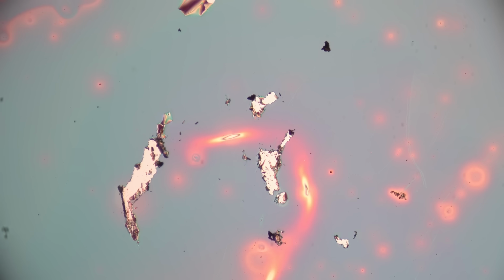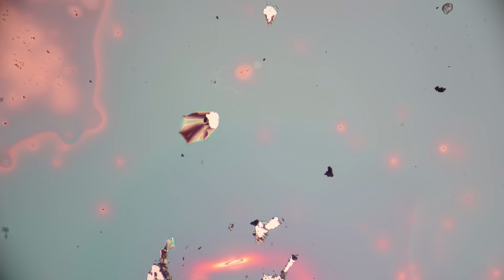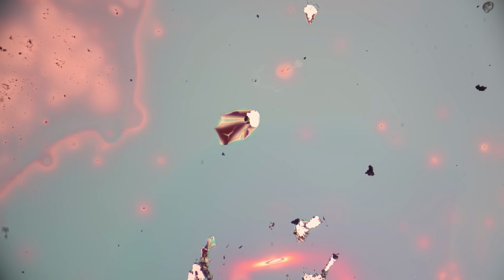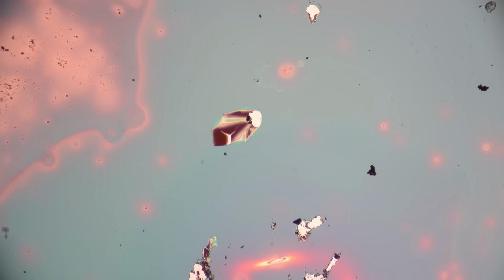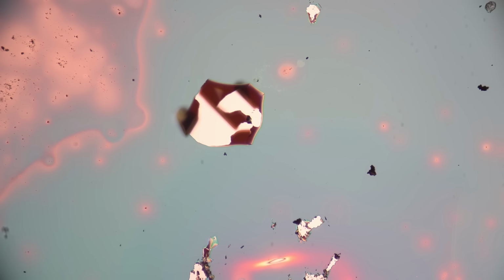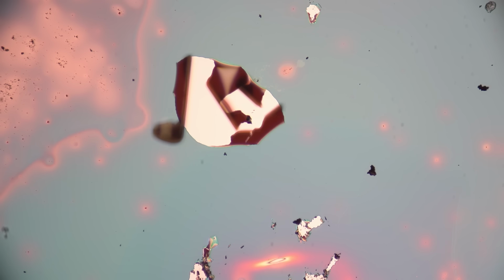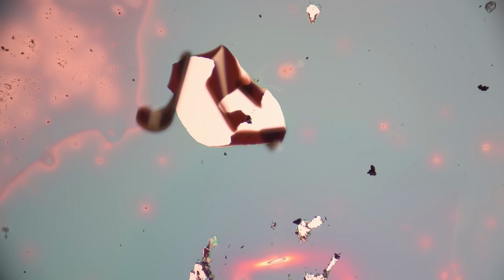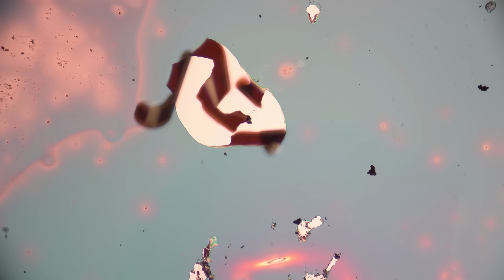I also found that 5 nanometers of titanium underneath the copper is an effective adhesion promoter between the substrate and the copper. It probably does mess with the semiconducting properties a little bit, because now you've got titanium mixed in, but yeah, it was easier than trying to do the pattern that they did. So 5 nanometers of titanium and then 80 nanometers of copper above it.